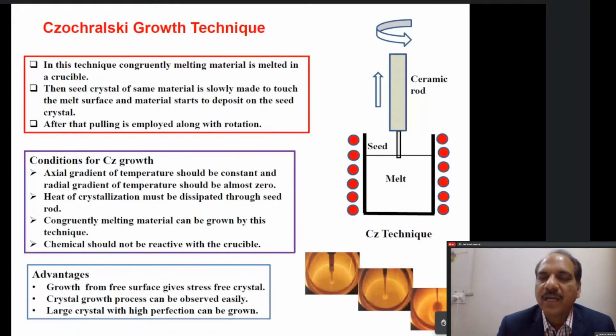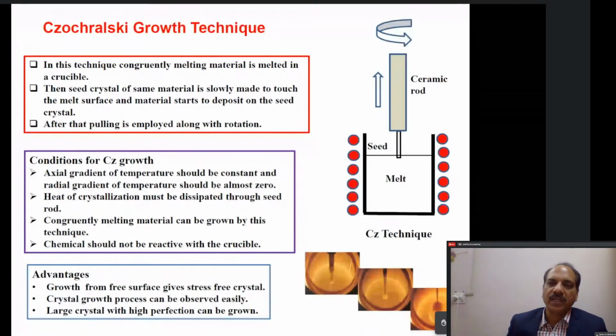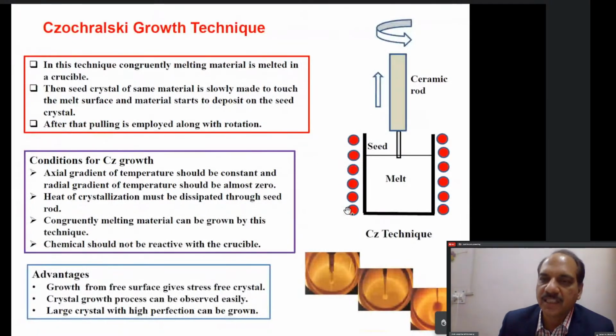Now once the lithium niobate is completely melted, we have a seed rod, and at the end of that seed rod is a ceramic rod to withstand high temperatures. That ceramic rod is coupled to a Czochralski crystal puller. And at the end of that ceramic rod, we have a lithium niobate seed crystal, which you see out here. This small seed crystal is tied to this ceramic rod, and this seed rod is dipped and made to touch the melt level. This is the melting charge. This is the crucible which I was talking about, and these red dots you see are basically representative of the furnace heating, basically your heater. Fine.